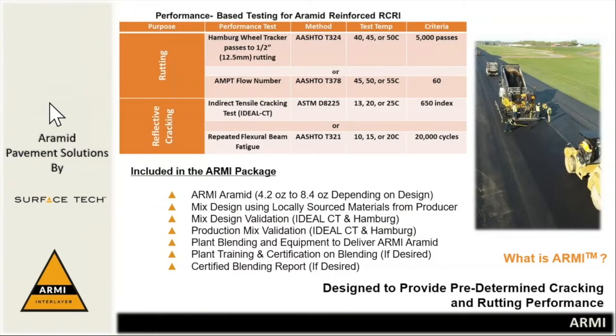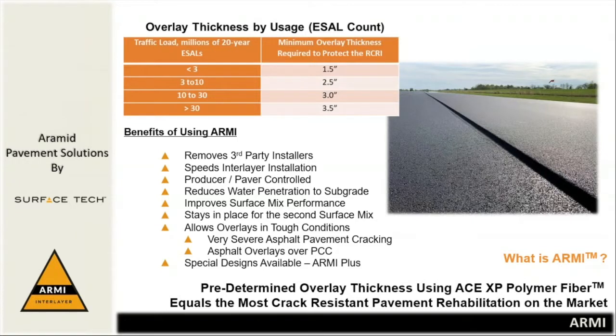The goal of the ARMI mix design is to achieve specific performance targets for rutting and cracking resistance as shown here. Surface Tech will prepare the mix design at a lab in Kentucky using materials provided by the local contractor. The overlay placed above the interlayer is a function of the traffic load. ARMI may be a solution to some of your most distressed pavements. When things are bad, you call in the ARMI.